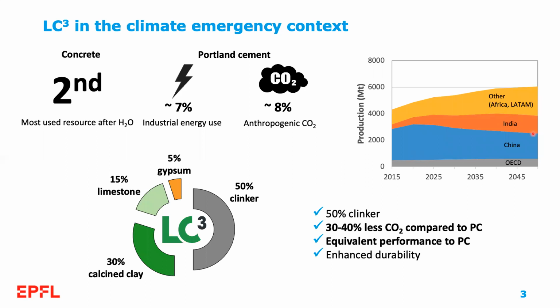LC3 is a blended cement that combines clinker, calcined clay, limestone, and gypsum. It allows us to reduce the clinker factor of this blended cement to 50%, saving 30 to 40% CO2 compared to PC, and offering equivalent performance to PC in terms of strength and enhanced durability in some exposure conditions.